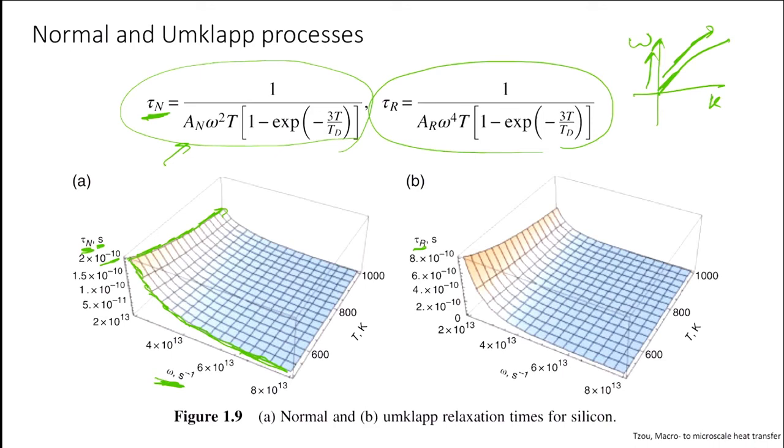As we increase the temperature, if phonons were previously scattering in 0.2 nanoseconds, they would now scatter in maybe 0.1 nanosecond at high temperature. So if two phonon collisions were happening after 0.2 nanoseconds, now they are going to happen after 0.1 nanosecond. It is decreasing with temperature because all the atoms and phonons are excited, so they could collide with each other much more quickly.